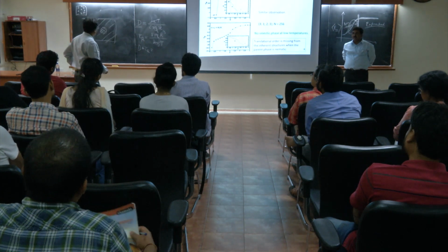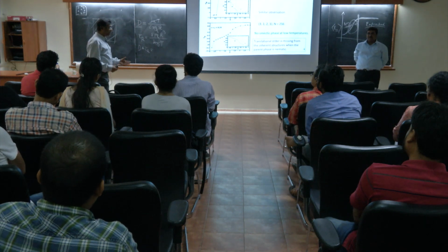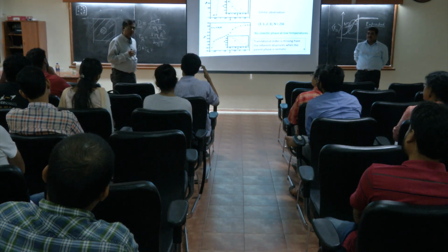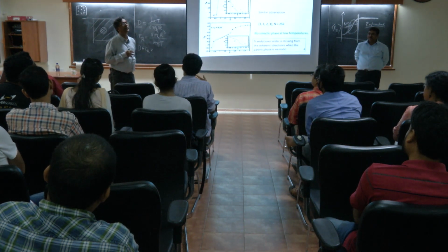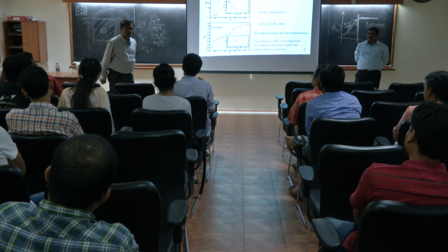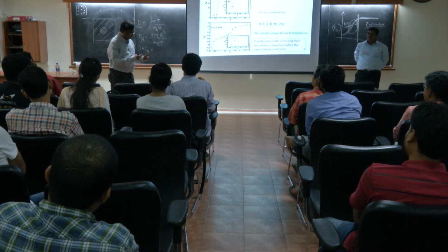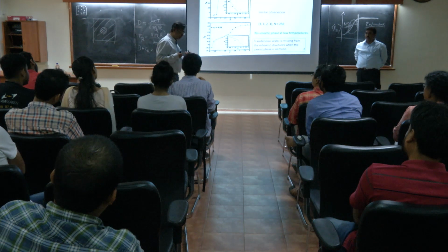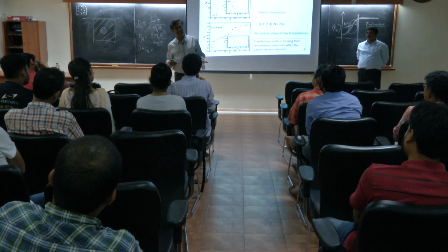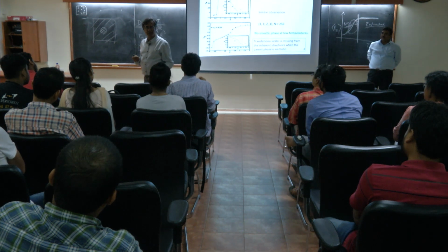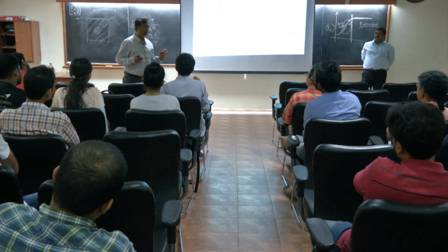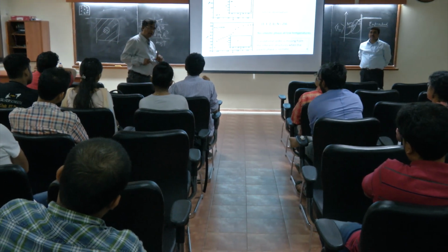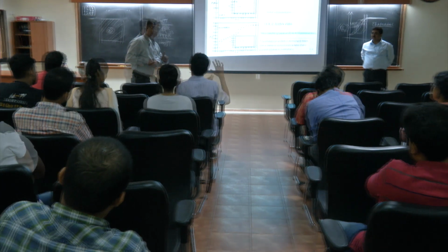Yeah, one of them I just showed you, density for example, or magnetization. Magnetization I sum over all the dipole moments, so it is a collective quantity. Density is a collective quantity. Another thing that we use a lot in liquids, in isotropic-nematic, is orientational order. Orientational order uses spherical harmonics, Y_lm. We do a sum over m of Y_6m, which is called Q6. Similarly with Q4, the tetrahedral order parameter for water. That is why, when I said order parameter, I said local quantities. They are local, but they are collective at the same time.